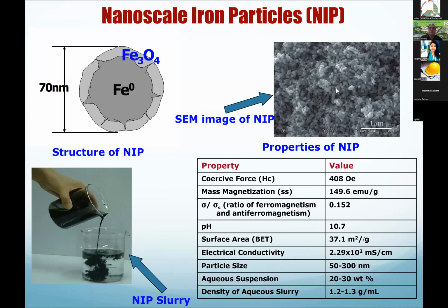And this is the SEM image showing how these nanoparticles look. And these are the properties of nano iron particles. The pH is highly alkaline, and the surface area, you can see, is 37.1 meters squared per gram. These particles are always supplied in aqueous suspension. So basically, they put it in a solution, and they supply it. So it won't be dry. But later on, some other companies created a process where they can supply these nanoparticles under dry conditions. But this Toda America, the Japanese company, provides the aqueous solution, which is 20 to 30% by weight.